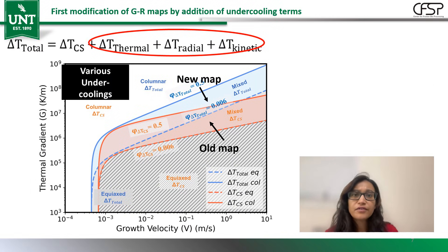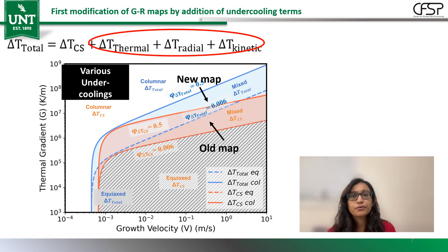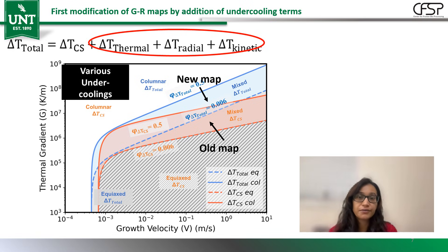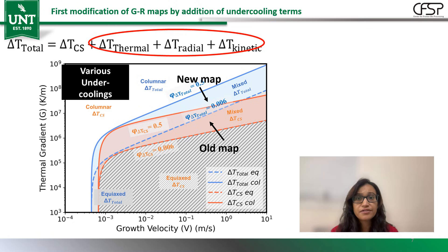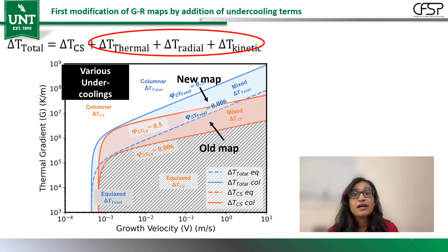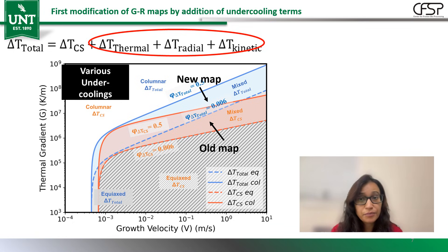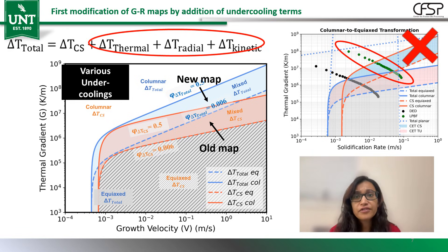To investigate, we went back to the fundamentals of what actually governs solidification. We found that the total undercooling also includes thermal undercooling, which is related to the velocity of the laser, and the radial undercooling, which is related to the dendrite tip radius, in addition to compositional undercooling. In traditional solidification methods like casting, many of these contributions are almost negligible, so GR maps simply ignored them. But in AM, with the extremely high cooling rates, these terms suddenly become very important. So we carefully added them back into the map and it improved the prediction.